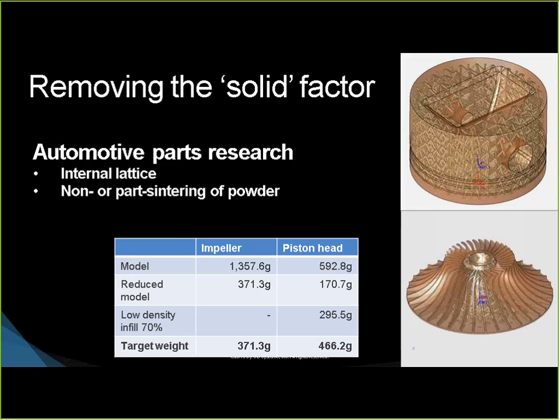Through a post-sintering process, leave the powder in, sinter it in place, and then, no more drainage, but still a reduced weight component. And so, again, I'd mentioned earlier that you would often want to drain the powder. In this case, it actually worked out to be a lighter weight component that was fully functional while leaving the powder in and sintering it in place. Next.